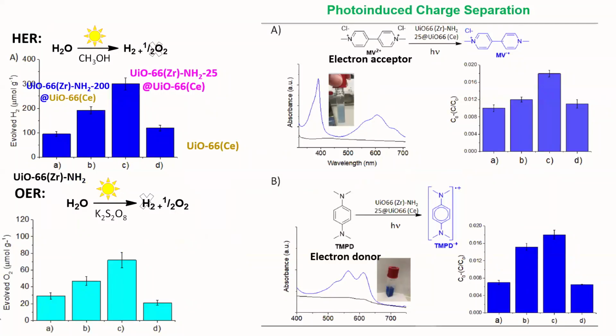So in order to understand the photo-induced charge separation, we have selected 2 probe molecules. One is called methyl viologen as a 1 electron acceptor, and the other one is tetramethylphenylenediamine. Upon irradiation, we have taken this photocatalyst, and this has turned to this MV plus, accepting 1 electron, and then the order of photocatalytic activity exactly matches with this irradiation. So the best sample exhibited higher charge separation, and you could see that the higher intensity was obtained for this. The same results were obtained for the electron donor, tetramethylphenylenediamine, and you can see that similar activity was observed for this also.